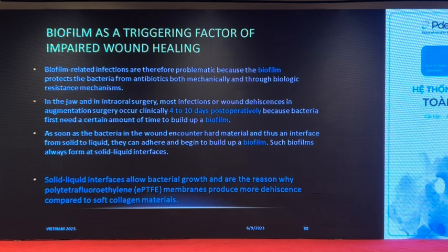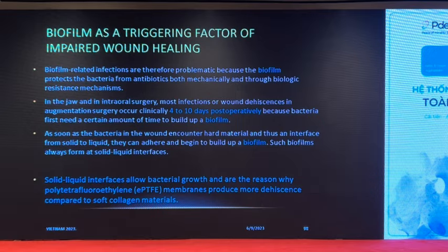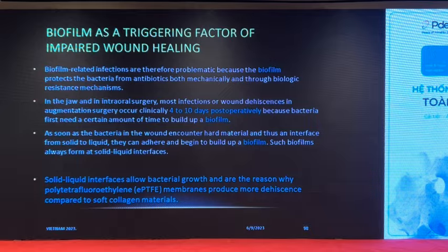As soon as the bacteria in the wound encounter hard material and thus an interface from solid to liquid, they can adhere and begin to build up the biofilm. Such biofilms always form at solid-liquid interfaces. These solid-liquid interfaces allow bacteria to grow and are resistant. Polytetrafluoroethylene or PTFE membranes produce more dehiscence compared to soft collagen materials.